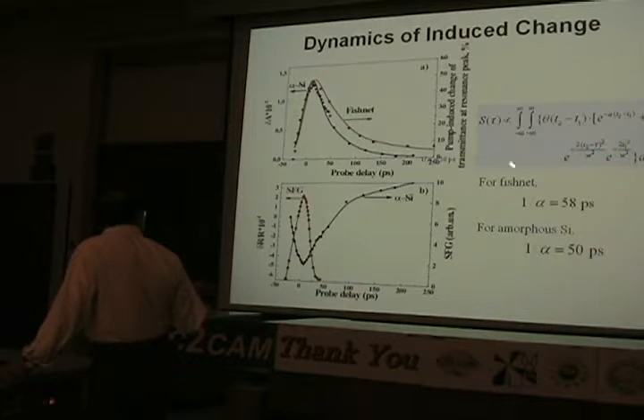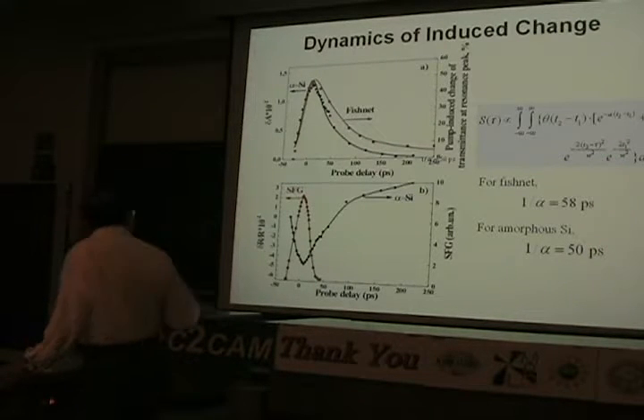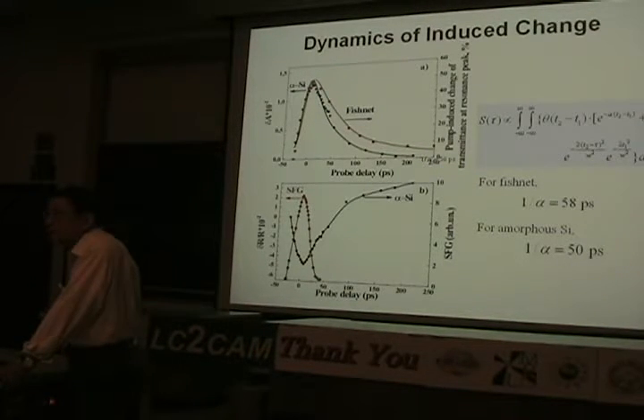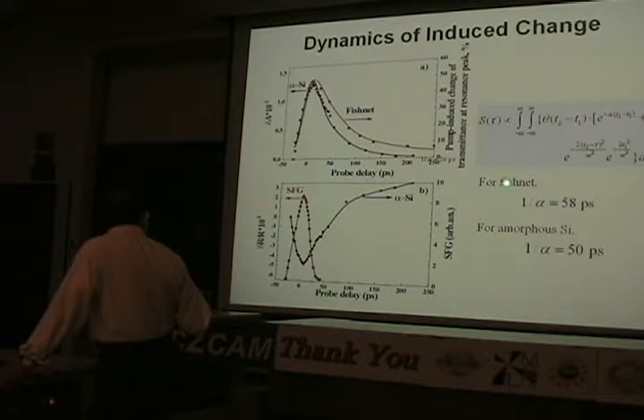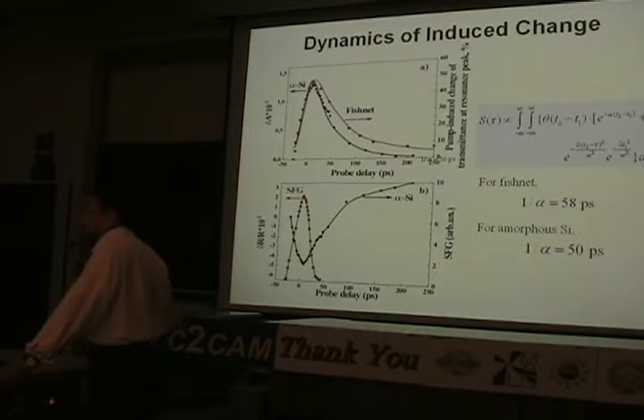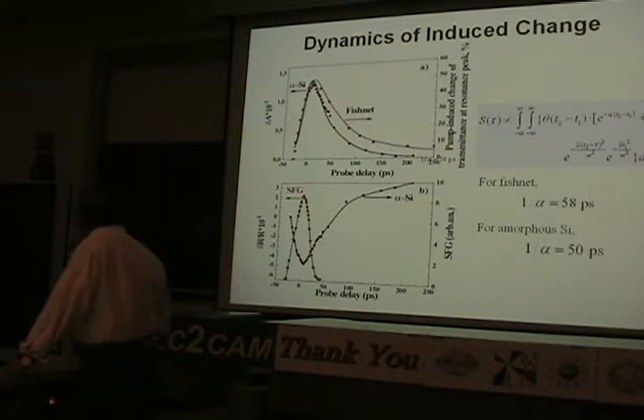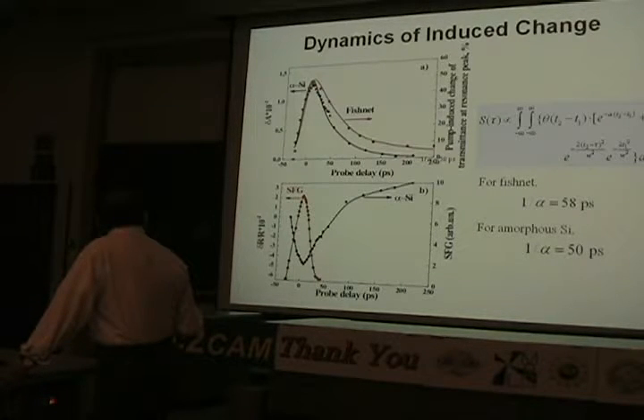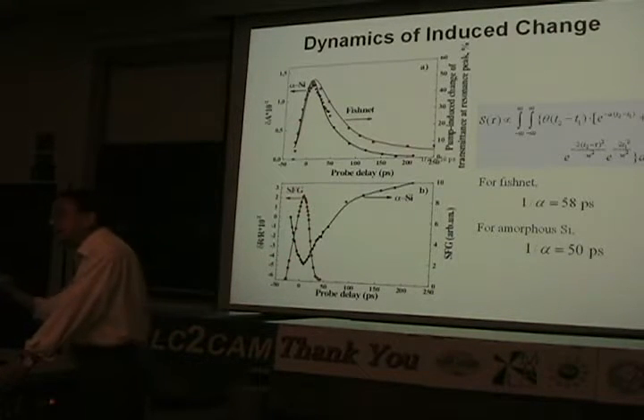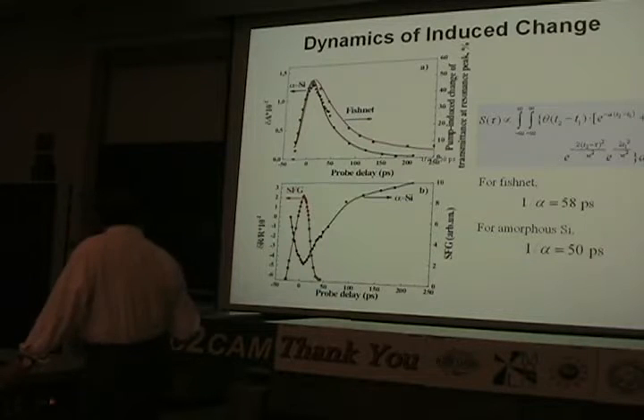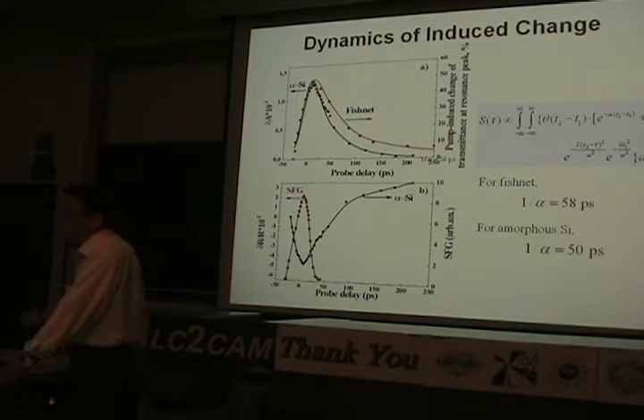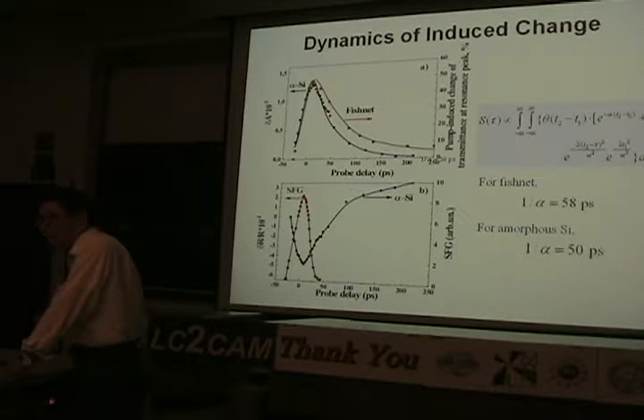So we use this simple exponential decay expression to fit the curve, and the solid curve fits very well. So it says that the relaxation time is about 58 picoseconds. Now, this is to also find the refractive index change is reasonable, and I'm not going to bother you with that. Indeed, at least semi-quantitatively, the agreement is good.